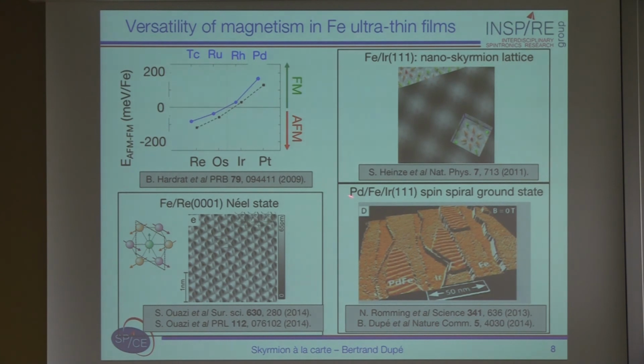So if you also change this kind of stacking and you go to iron on rhenium 0001, you see that these two things are again changed, and then you have a Néel state, which was also seen in the group of Roland Wiesendanger in Hamburg.